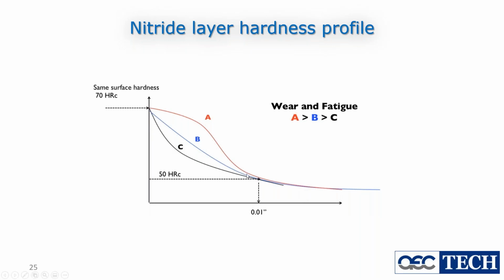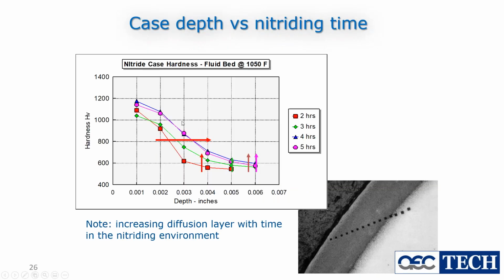B has got a bit more depth, and A has got a lot of depth. If you start to get any wear in the surface, you really have to go quite a long way before you start to see the softer steel that you see in this profile. So we're looking for nitrided profile A from our process.